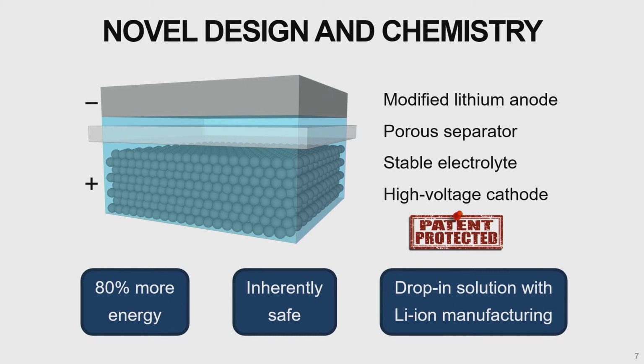So we start with a new electrolyte, and that's really the core of the innovation, a completely different set of solvents and salts that's ultimately extremely thermally stable and also chemically stable, which allows us to actually integrate more energy-dense components. Starting from that new electrolyte, we've then put in a lithium metal anode, which replaces the typical graphite anode in lithium-ion batteries with something that's substantially lighter on the anode side, roughly 10 times lighter. So the anode pretty much disappears from your weight equation.